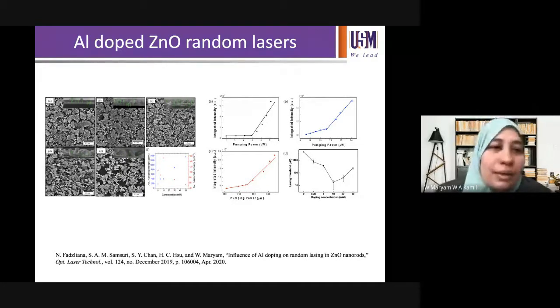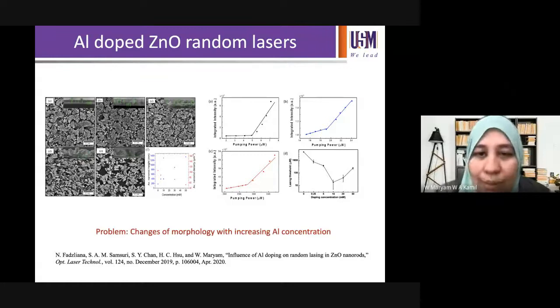What we saw is that yes, there is a certain doping concentration where the threshold is low, but the issue highlighted by the reviewers of the paper, even though it was accepted, is that when we change the doping concentration, we change the morphology. You see that the size changes a lot. By the time it reaches E, where the concentration is about 50 millimolar, it becomes bigger, fatter, and the distribution is no longer as much, right? So there is an issue of whether it is due to aluminium or due to the morphology, because random lasing relies on the scattering element. This was an open question at the time.